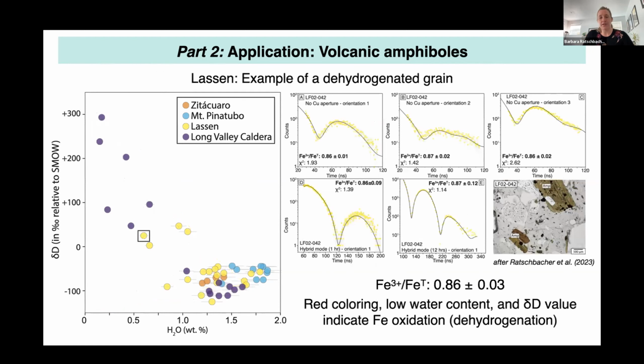Okay, let's have a look at some of the results. Some of the spectra we collected using single-crystal Mössbauer spectroscopy, beamline 3. So let's start off by looking at an example of a dehydrogenated grain. This is a grain from Lassen, which has lower water contents and heavier hydrogen isotope composition. And we collected spectra in 24 bunch mode and hybrid mode along different crystallographic orientations. And we were able to find a chemical model for this one crystal fitting all of the different spectra collected along different orientations.